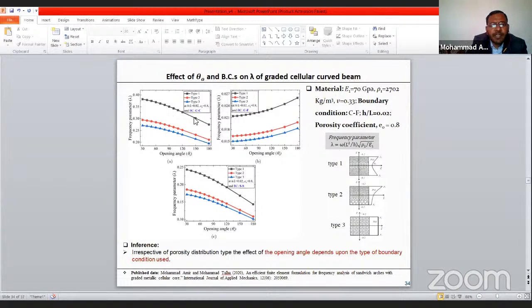So we found that, in the graph plotted for frequency parameter versus opening angle, on increasing the opening angle the frequency parameter decreases for the clamped and simply supported boundary conditions, while in the case of the clamped free boundary condition it increases. It can be concluded that the effect of opening angle also depends upon the type of boundary condition used.